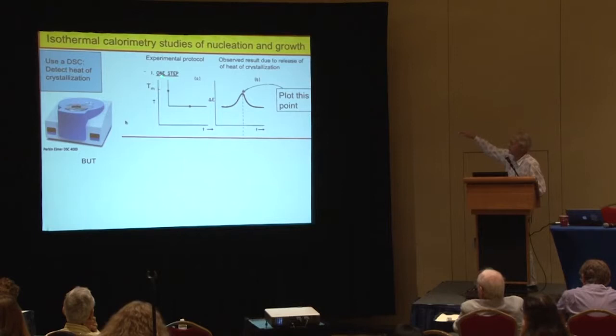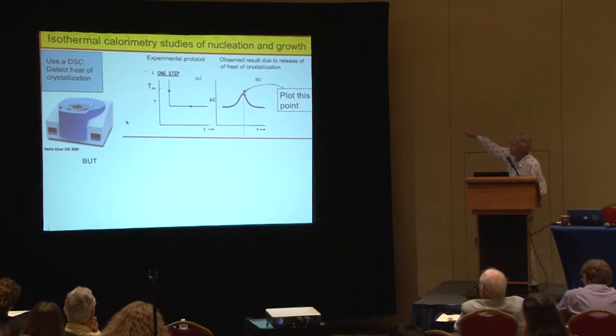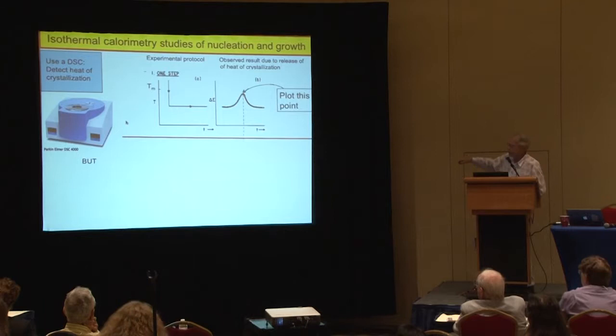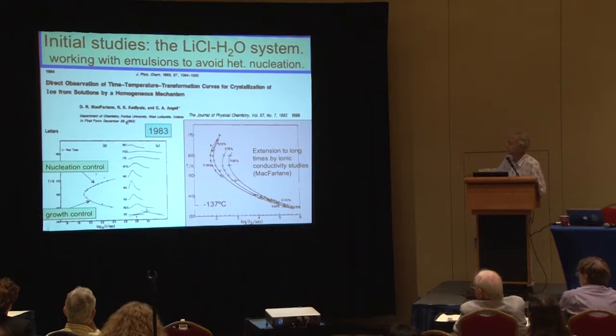We drop the temperature through the melting point and then simply to a pre-assigned temperature and simply wait. After a little while, nuclei appear and then the crystals grow, and they release the heat of fusion, which the calorimeter picks up as a peak. Then we take that point, which corresponds to about 50% of the crystallizable water having frozen out, and we plot it. And we get this series of peaks here, and I think maybe this was the first use of the differential scanning calorimeter to determine the TTT curve.